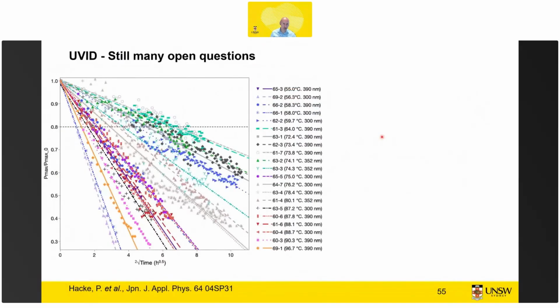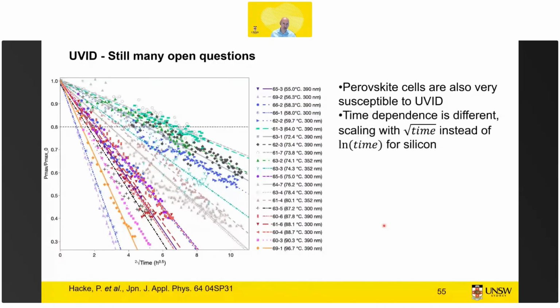If we then look at perovskites, perovskite seems to be sensitive to many different stress factors. UVID is one of them. You see that just 100 hours for these cells tested here got you down to 30% of the initial performance, which is not good. There is very strong wavelength dependence, very strong temperature dependence, and it scales with the square root of the time. So unfortunately, the absolute decrease is a lot worse, and it also degrades a lot quicker. So for perovskite, there's still a lot of work to be done.